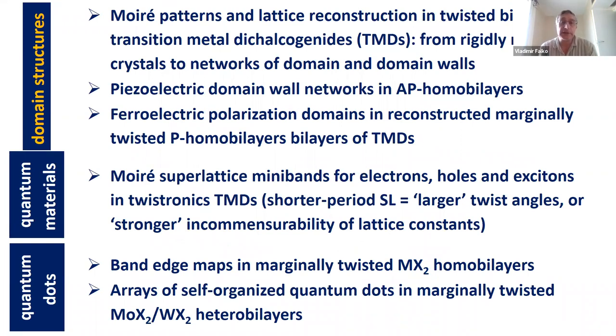It happens that even despite weak van der Waals coupling between the layers, because those layers are so thin, there is reconstruction of the layers happening. And the first thing to do is to establish the conditions when this reconstruction takes place. And what we find is that reconstruction occurs into networks of domains and domain walls. And then there is a bit of classical physics of those structures related just to lattice reconstruction and the piezoelectric effect that we need to take into account, having in mind that the individual layers have no inversion symmetry.